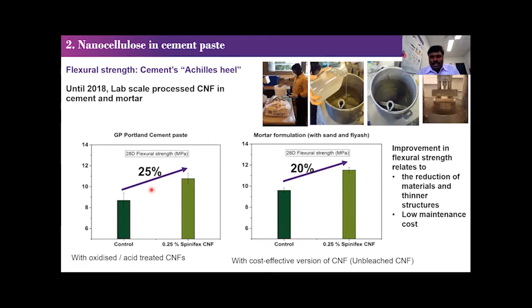We started with simple cement, the type 1 cement, which is general purpose cement. We tested about 6 types of nanofiber with different surface chemistry, where we did oxidation and acid hydrolysis to get different surface chemistry. We got really good properties with the oxidized and acid hydrolyzed nanofibers, about a 25% improvement in the flexural strength of just the cement. Then we also tested with sand and fly ash, which is a mortar, and we got up to a 20% improvement. This was done at lab scale processing.